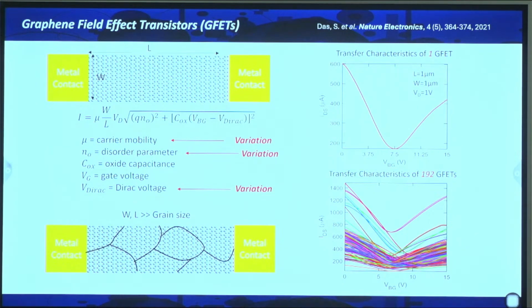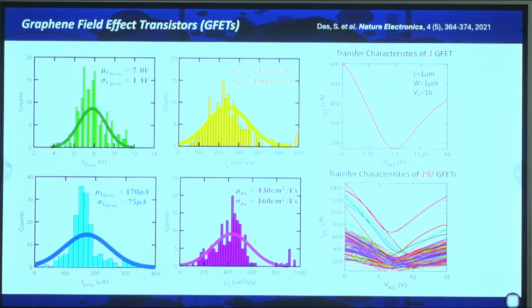Now the question is how. So we see that a lot of these parameters, this Dirac point, this different current, they all follow a Gaussian distribution. So that means that they are really random in nature, right? Because whenever they follow a Gaussian distribution or a uniform distribution, we say that they follow some probabilistic law, right? So this can then be used for the... these are identical devices. Identical devices whose characteristics are different because of the fact that you have grain boundaries, right? You have mobility being different, right?